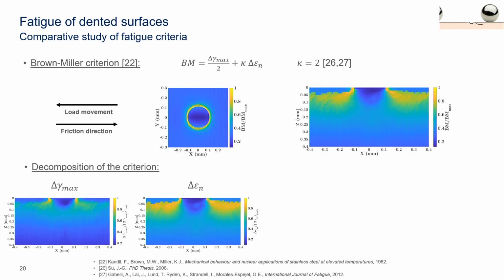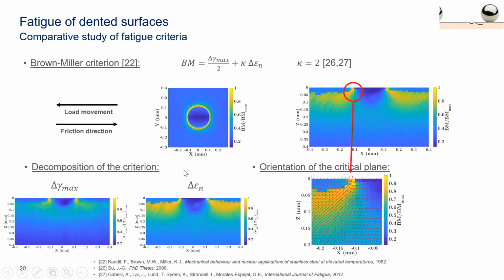This is for the Brown-Miller parameter. The advantage this time is that it is not the stress which is important, this is the strain. Here you have the shear strain, and here you have the normal strain. When it is tensile, especially, it is quite dangerous. And delta means this is the amplitude between the minimum and the maximum. Here again, you can find some interesting results, especially because we find the good location for the damage, and also we have here the principal direction. Then you can see that it corresponds to the crack propagation, what we are looking for.